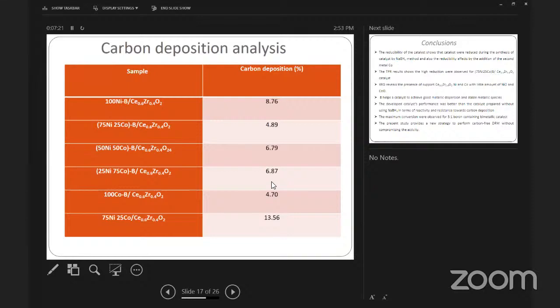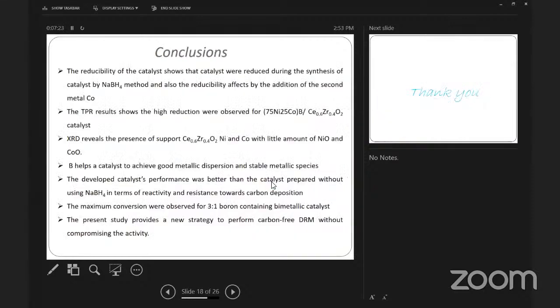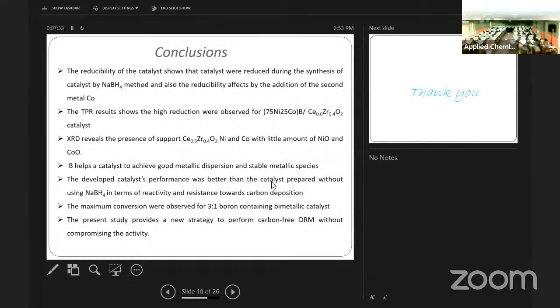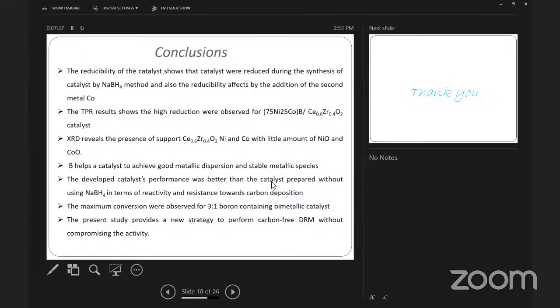So here, I am concluding my work. The reducibility of the catalyst shows that the reduction of the synthesized catalyst using NaBH4 was higher, especially for the bimetallic catalyst. The TPR shows a high reduction was observed for the 75%, 3:1 ratio bimetallic catalyst.